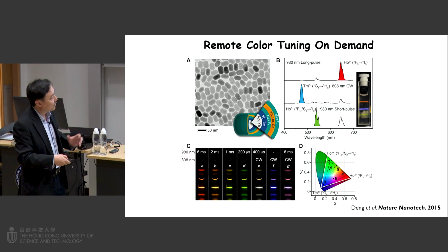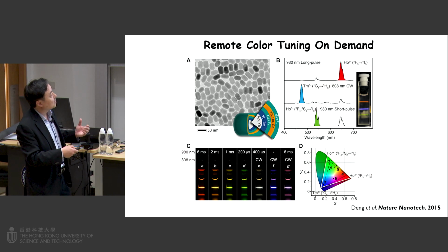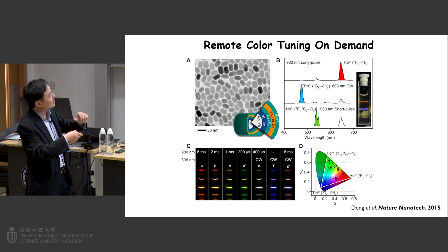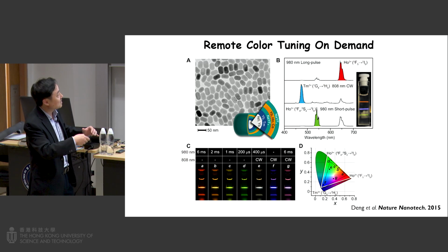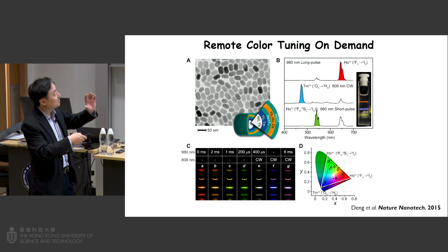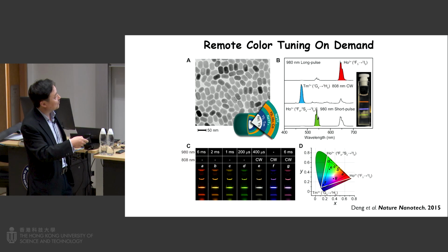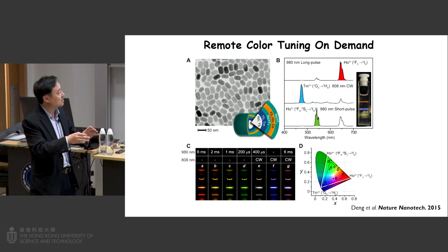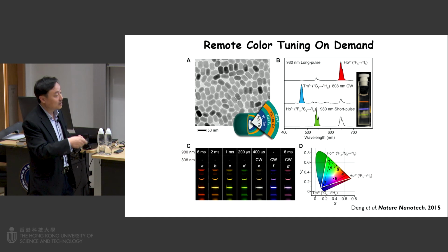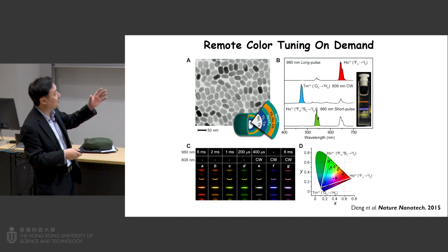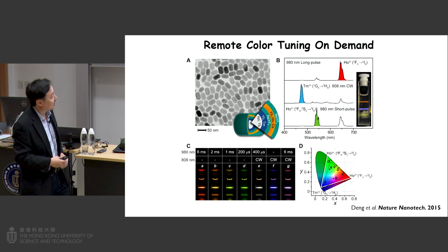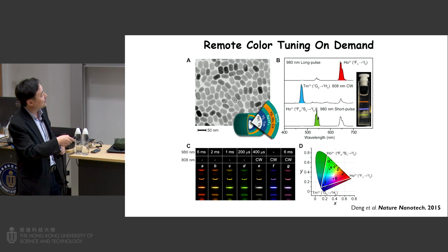Landon, a very good student, came up with this multi-core-shell structure. It's a complicated design here. You can see originally the core particle is spherical, but upon multiple syntheses, the particle is elongated. There may be some minor phase transitions, but it still is a core-shell structure. Every layer has a certain combination of lanthanide ions. So it turns out the design is very, very important. How he came up with this wonderful design, I often talk to him about.